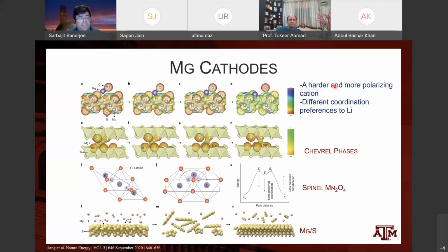So the challenge with diffusing magnesium is that it's a harder and more polarizing ion. It's got very different coordination preferences to lithium. So again, a lot of the best work, starting from work done by Doron Aurbach's group, has been in these Chevrel phases. One of the challenges is that the magnesium electrolyte needs to be desolvated at the interface. This is not as much of a challenge for a lithium electrolyte, because if you've got a lithium plus X minus, usually they've been designed to very readily dissociate. But in magnesium electrolytes, because of the 2+ nature of magnesium, the dissociation oftentimes is into MgCl plus and X minus, and that MgCl bond can be difficult to break, so that desolvation has to happen first before the ion gets into the system, and then it has to migrate to the lattice.